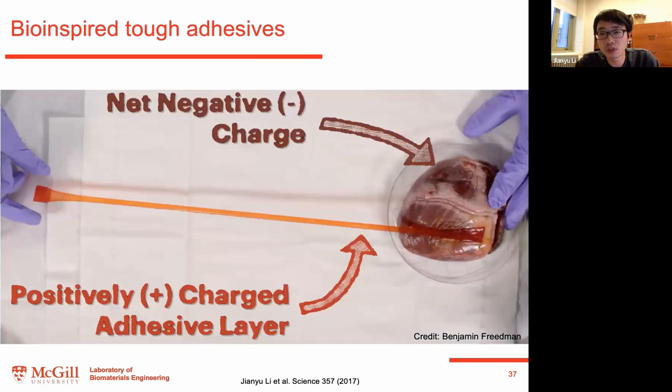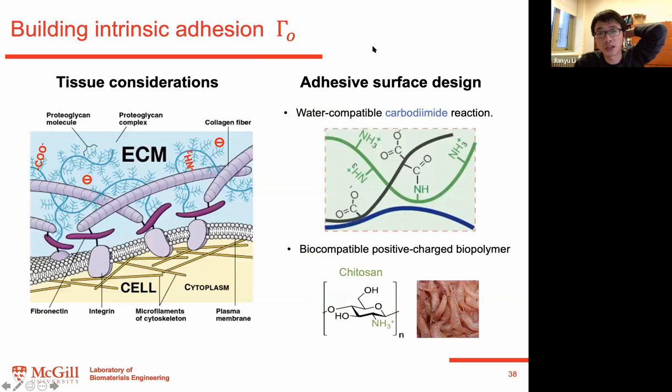So that is a demonstration of the adhesion and also the stretchability of our system. It can be stretched to a large stretch ratio, and how do we enable that? That comes to the design. The design tries to optimize the two contributions, right? We need to optimize the intrinsic adhesion by having a strong interfacial bond with the interface. So in this case, we use a hydrogel which can have amide bond formation and also electrostatic interaction with the often negatively charged tissue surface.